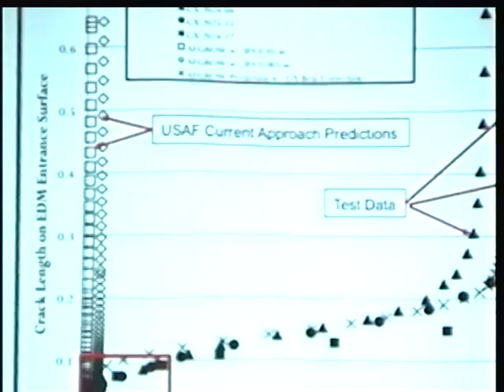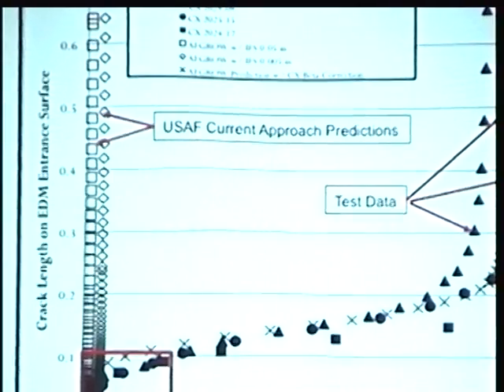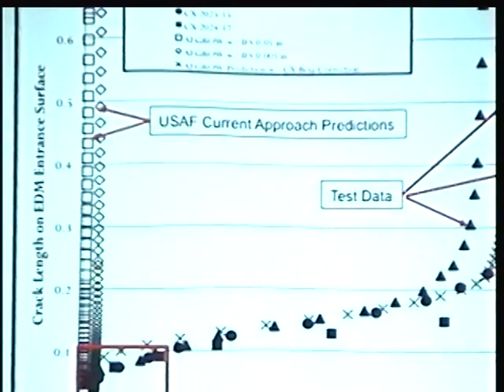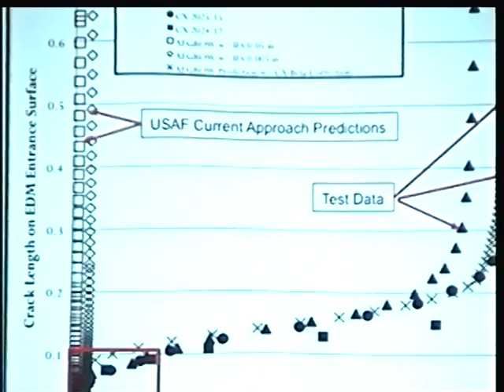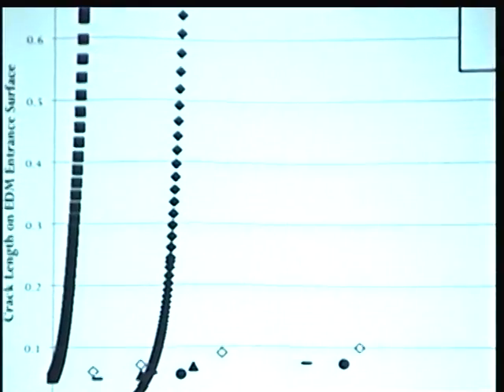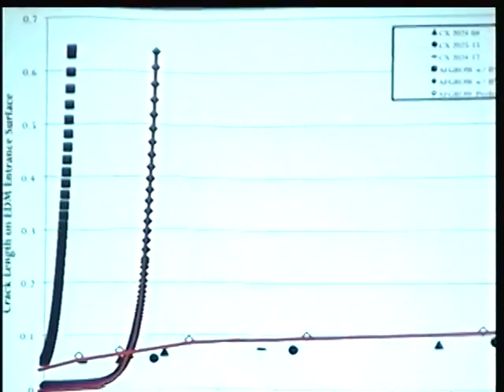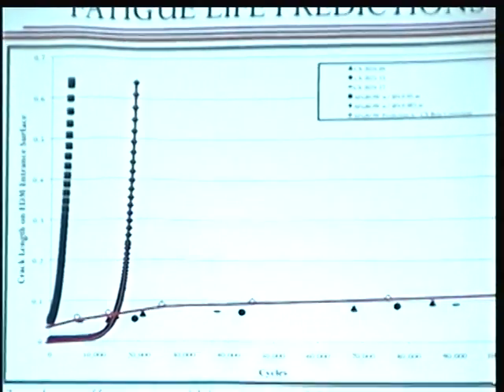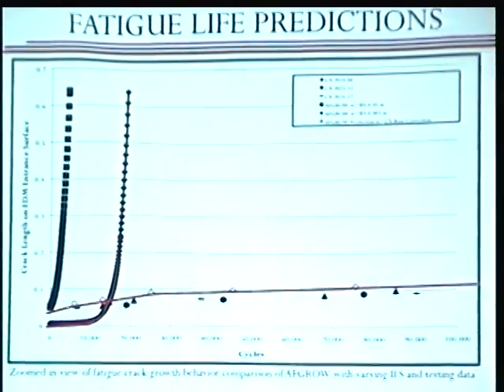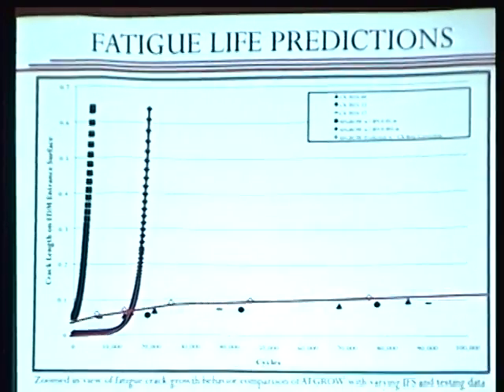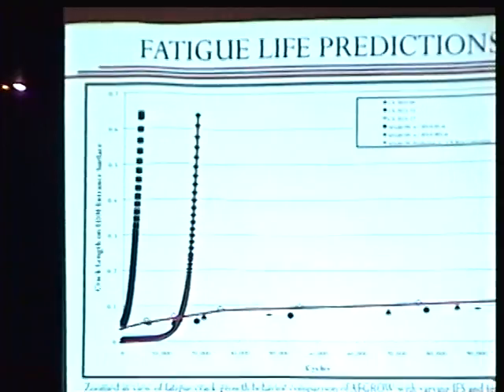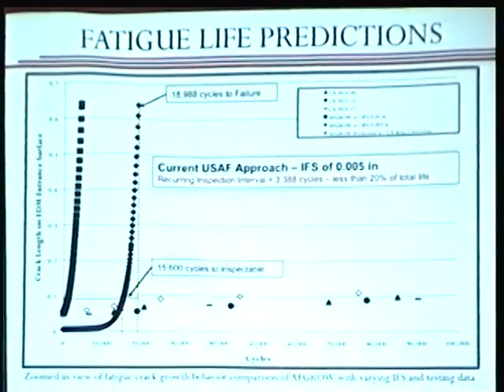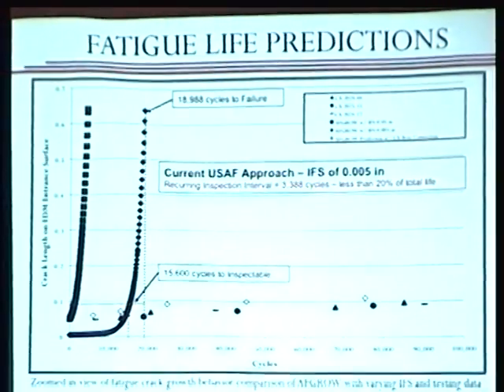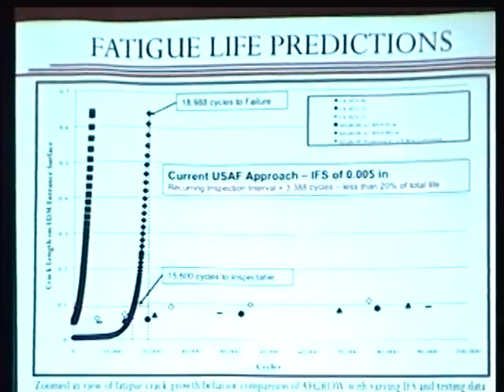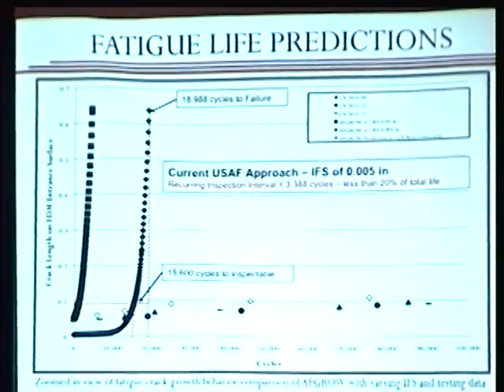But the other thing that's very important when you start talking about NDI, you start talking about sustaining aging aircraft. You remember, we have to manage from what we can detect to what is critical, not from some assumed initial flaw size. NDI comes into play and is very important. With our current approach, we're really limited because we assume the crack's really small and it stays small, and then all of a sudden it goes fast. Just based on the overall model and reducing the initial flaw size, you don't get a lot of benefit.